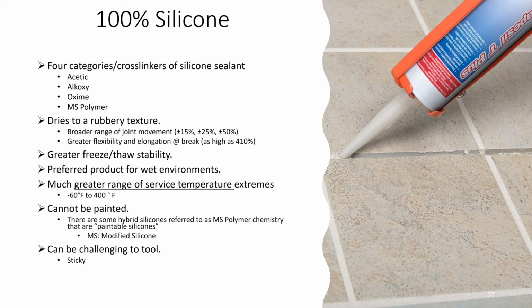Greater flexibility and elongation is typical with this rubbery texture, so you see that with the testing at 410%. It's freeze-thaw stable, and it's the preferred product for wet environments, as I just mentioned. The service temperature range is really large there, minus 60 F to 400 F, so it's very impressive versus a siliconized acrylic. It cannot be painted though, and it is somewhat difficult to tool at times, depending on your technique.